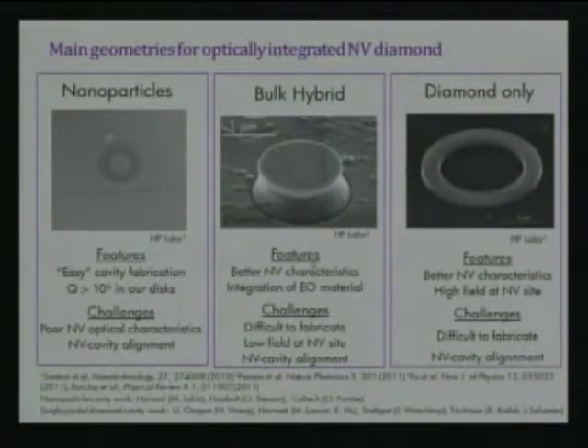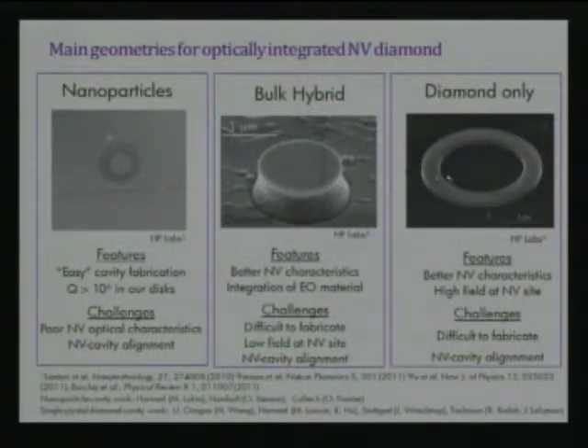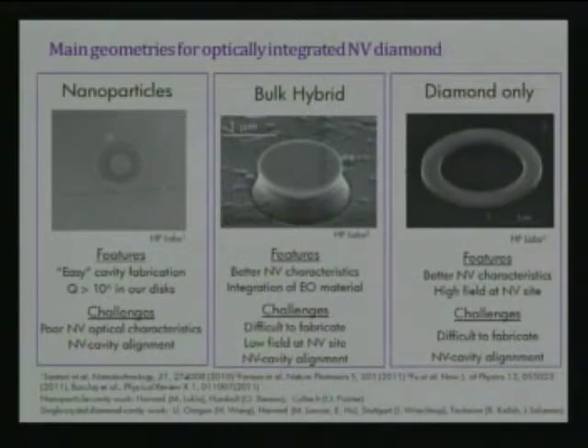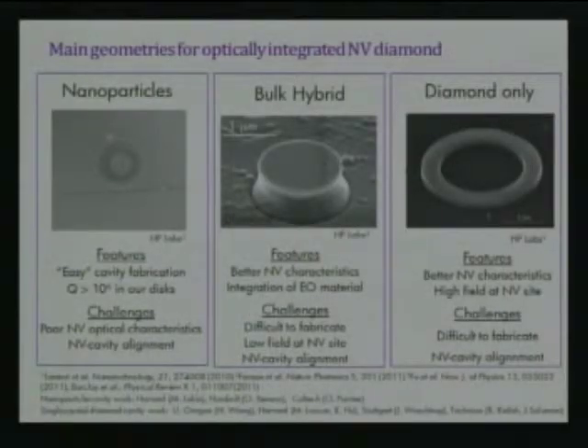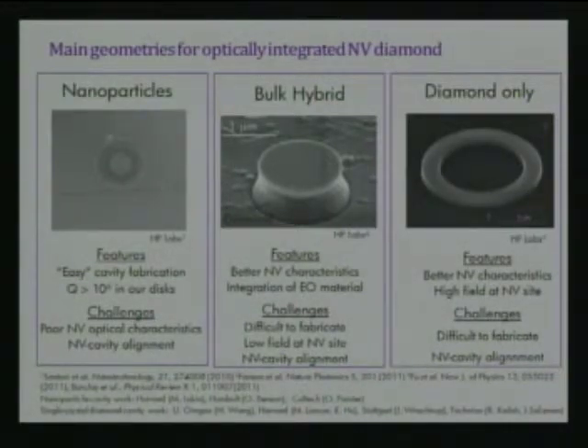In my very last year at HP, 5-micron thin films of diamond became commercially available. You can take a 5-micron thin film of diamond, stick it on a low-index substrate, thin it all the way down to 200 nanometers, create a ring resonator, and have the electromagnetic field propagating around the ring interact with a nitrogen vacancy center that happens to be in the ring. This has the advantage of better NV characteristics because you're in single crystal diamond with a high electromagnetic field at the NV site. A huge challenge is working with 5-micron diamond substrates and trying to fabricate with them.